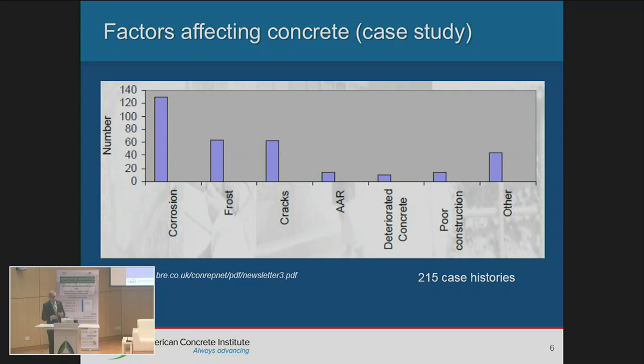The repair industry really evolved over many years. Back in the 80s, two independent studies were published, one in the US and one in the UK, where people wanted to find out, if we have repair work, how long does that repair work last? Here I'm showing one study that was done in the UK. We're looking at about 215 case studies. If you add all those up, they total more than 215, because a structure could have more than one failure or deterioration issue, so it would be documented under more than one. Could be corrosion, could be freeze-thaw, could be deteriorated concrete, or poor construction.